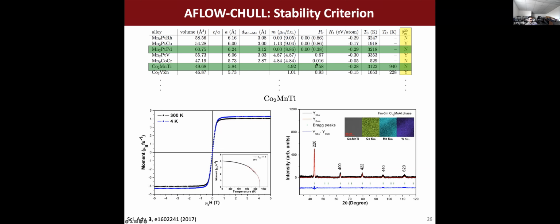So one of the criteria here is we looked at the stability criterion. So we asked the question, which systems are really robustly stable? Is their stability criterion greater, is that distance greater than 30 meV per atom? This is greater than that room temperature threshold that I defined earlier. So if they're really robustly stable, we picked those out for additional analysis. And so this was one of the criteria that helped us reduce from 200,000 down to 4. And of the 4, we were able to synthesize 2.